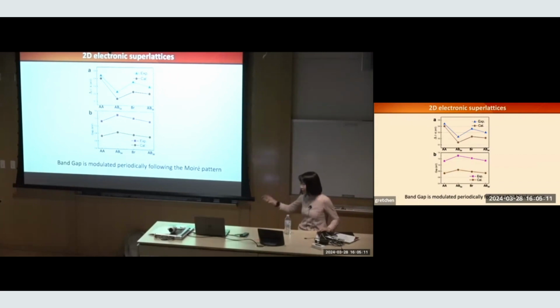It's because fundamentally first principle calculation has a trouble defining what's a band gap. But importantly, the trend at different local stacking, the experiments and the calculation agree with each other. So we know their band gap modulation, and that's where you would find electron preferably sits at one place versus the other place.